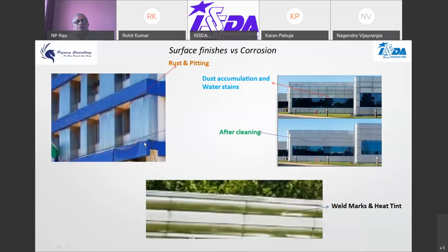Some examples of corrosion by using the wrong stainless steel finish. On the left hand side, in this particular building, you can see that they have not only used a ferritic grade on the sea shore, which is prone to corrosion, they have used a ferritic grade with a number 4 grain finish. If they had used 316L with mirror polish, this problem would not have happened. And so the whole thing got rusted, and despite a lot of cleaning, it's still there and the building looks very bad. On the right hand side, again, due to the wrong finish used, there were water stains, etc. And of course, after cleaning, you could get this. So this is a good example because it did not rust. And this is another example where there are weld marks and heat tints because of poor fabrication.